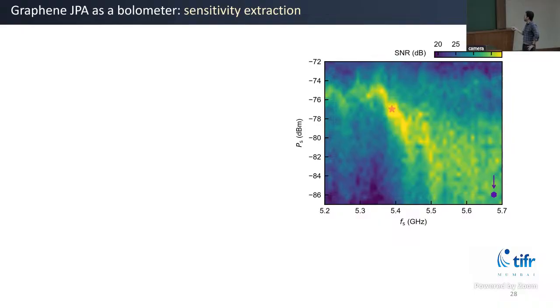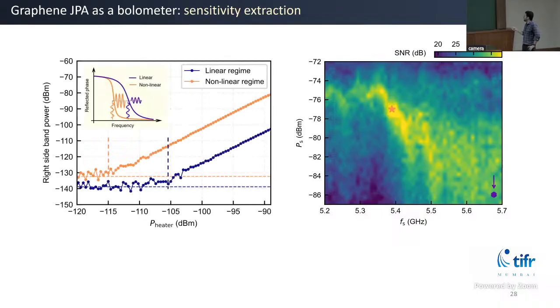Now I'll compare two regimes. One is the linear regime, marked by this purple hexagon, and the other is the non-linear regime, this orange star. Here you are seeing the sideband power as a function of heater power. At very low heater power, your bolometer is unable to sense it, so the signal is hugging the noise floor. When it can sense it, your sideband power starts to rise. And what we found is that, between the linear and non-linear regimes, you can get a large enhancement in your sideband power, which is also explained by this schematic here, because the resonance becomes very sharp in the non-linear regime. And on top of that, we have this JPA that enhances the signal power.